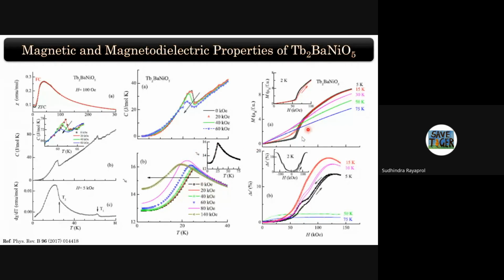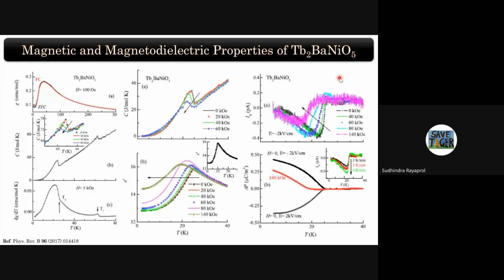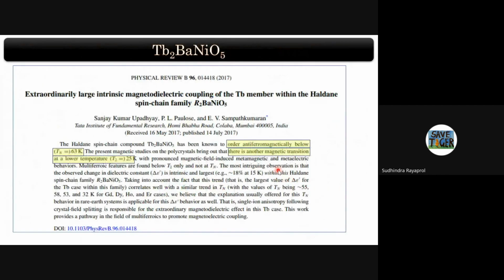But if you look at field induced magnetization or the magnetodielectric effect, you see that there is a hysteresis, which shows this metamagnetic kind of transition at intermediate fields, and it has a field dependence also. And this is the temperature at which we saw the pyroelectric current, and if you integrate that, you find that there is a polarization which is seen only below this 25 Kelvin. Right. So what could be the origin for that? If you look at the paper, this was the transition observed only at 25 K, not at 63 K. And it was the highest among all the rare earth based systems which were studied.